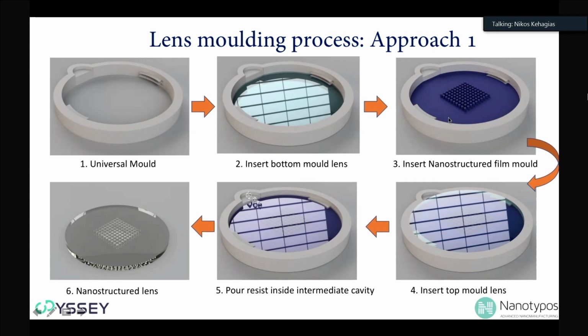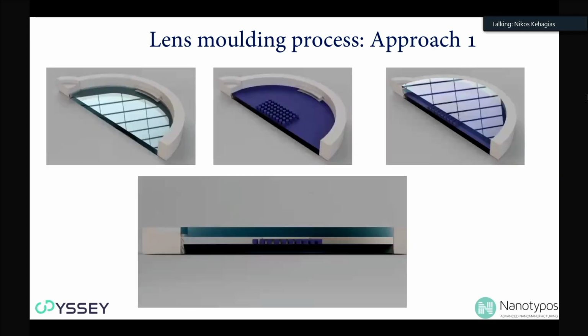We attach to this quartz substrate a thin film, our working mold. You attach on top, you close the mold with another quartz capping layer or substrate, and then within the gap, which is within the ring here, we insert the UV material from which the lenses are made. So we follow the same technique.